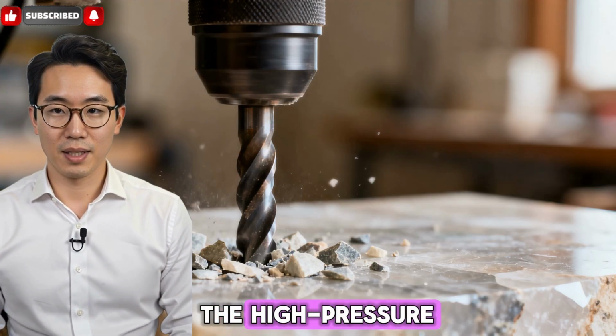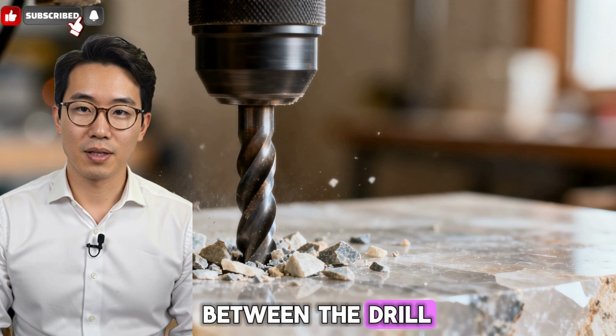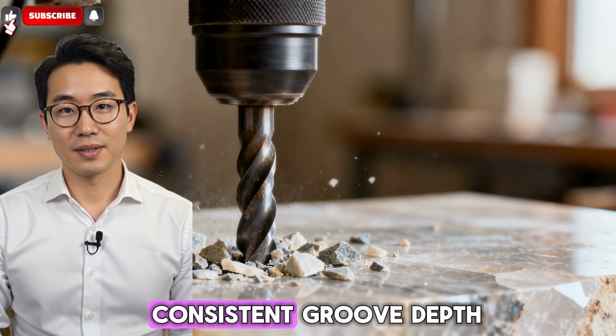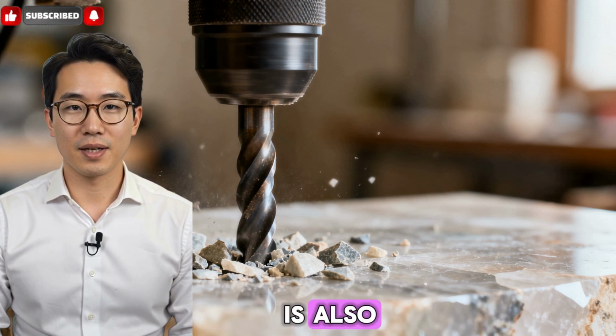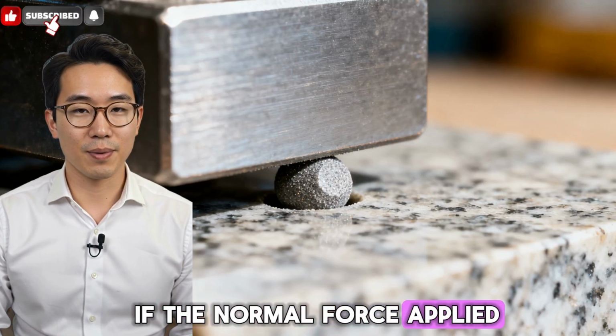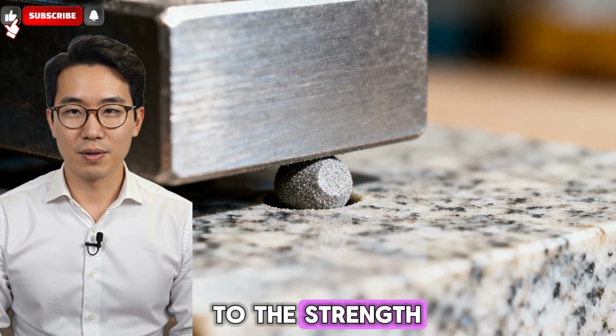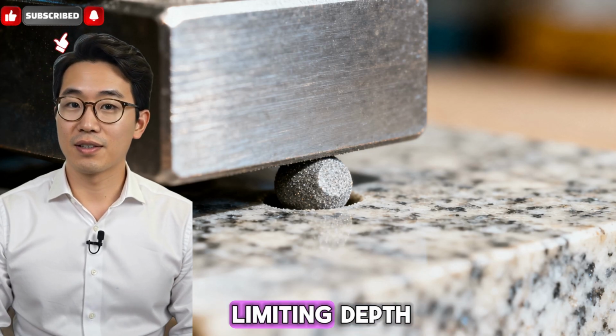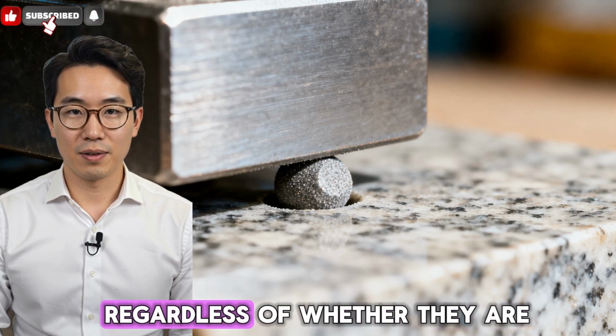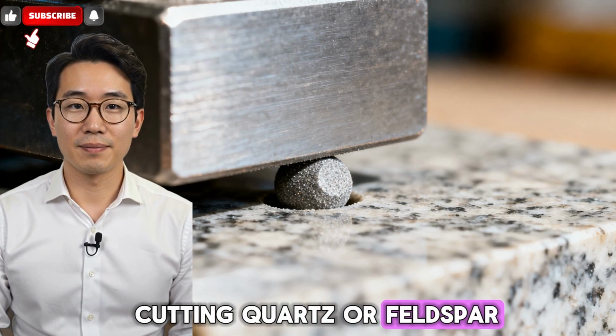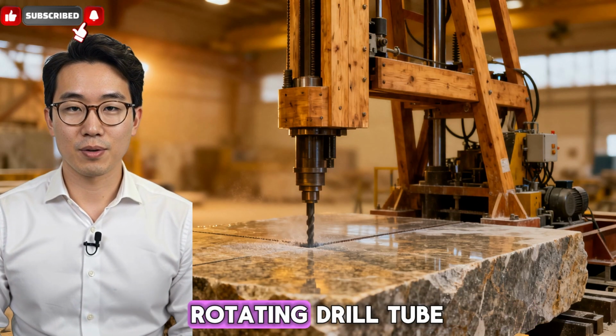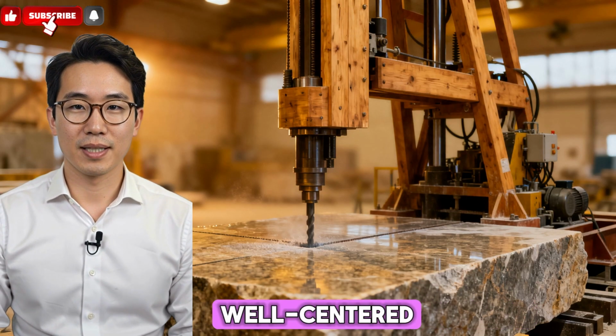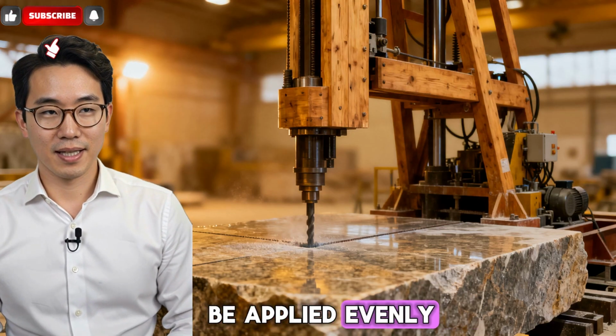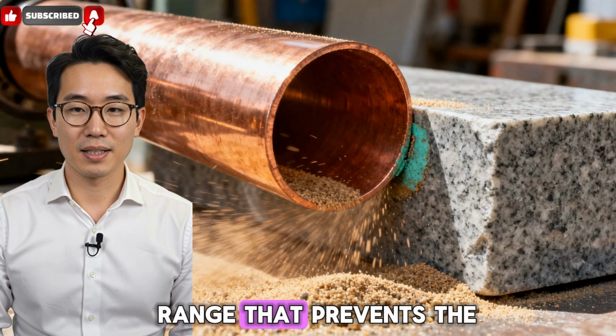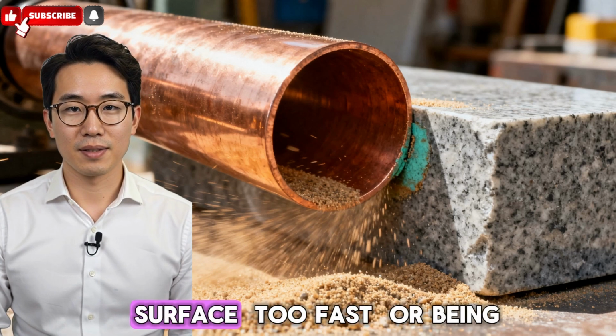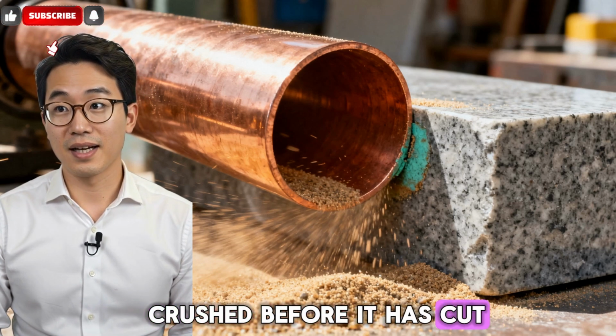The high-pressure argument, that the contact pressure between the drill and the core surface was high enough to drive consistent groove depth regardless of mineral hardness, is also physically coherent. If the normal force applied by the drill is sufficiently high relative to the strength of the abrasive grain, all grains reach their limiting depth before being crushed or expelled, regardless of whether they are cutting quartz or feldspar. Achieving this consistent high-pressure contact across a rotating drill tube requires the drill to be well-centered, the downward force to be applied evenly, and the rotational speed to be controlled within a range that prevents the abrasive from either skipping across the surface, too fast, or being crushed before it has cut, too slow.